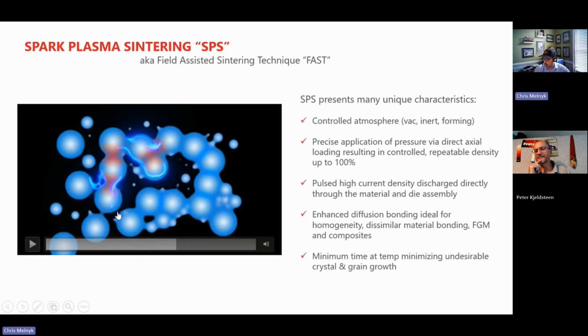And I think basically what happened, the best I can understand, is that somewhere in the mid 90s, if you're densifying, say, aluminum as an example, aluminum particles, and you have these nice spherical particles, if they're passivated, they're going to have an oxide layer on them. And so the aluminum is sitting there and it's got a nice oxide, like an eggshell on the egg. And then when you go to hot press something like this, the temperatures that you're processing aluminum are much lower than the stability temperatures of aluminum oxide, which is a much higher temperature ceramic. So you end up seeing all those previous particle boundaries in your final consolidated component. You would end up seeing all these nice eggshells touching each other, and the bonding between the aluminum oxide and the aluminum oxide is often insufficient when you're only processing at aluminum temperatures, 500, 600, in that range. So that's a perfect place for a crack to propagate and have a failure.